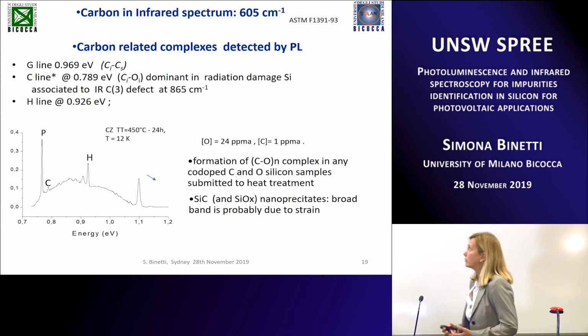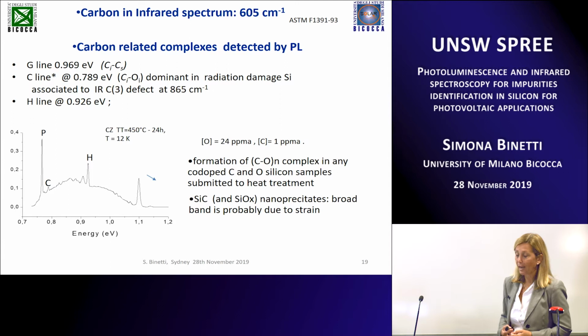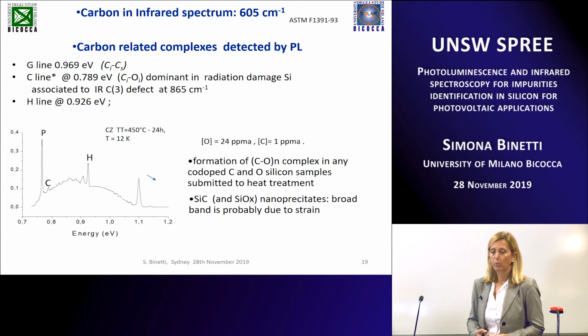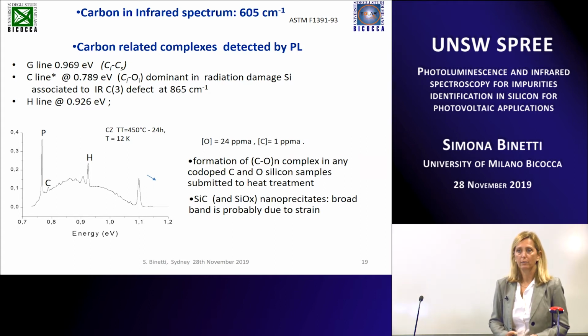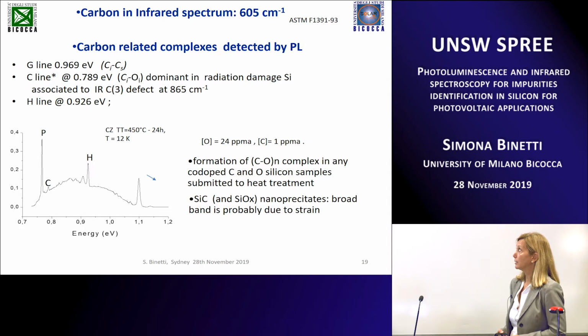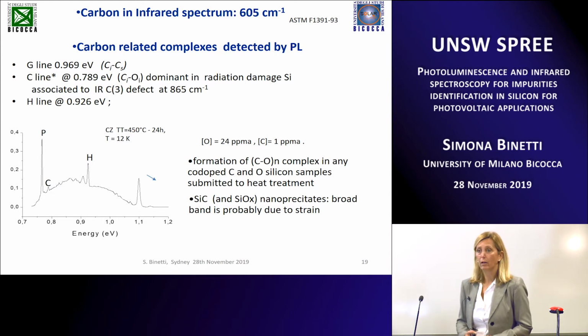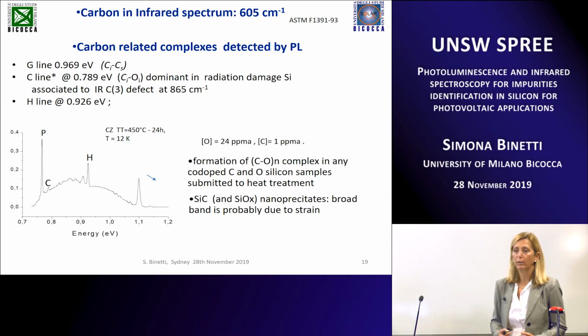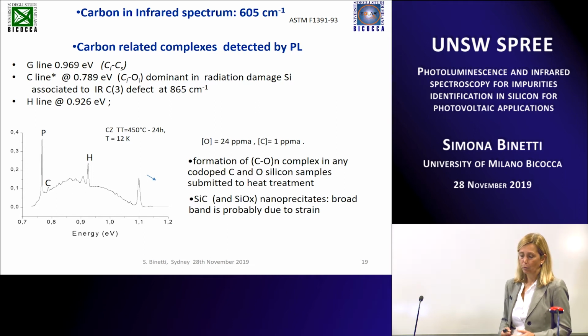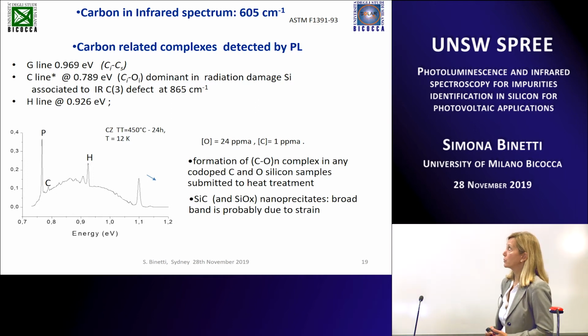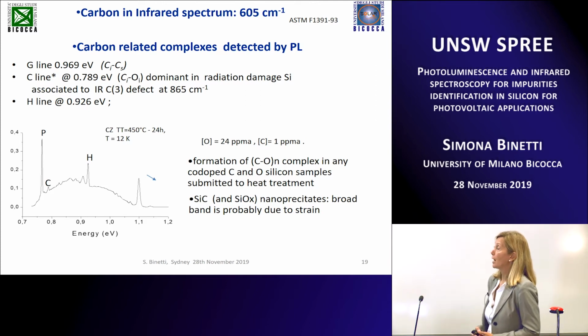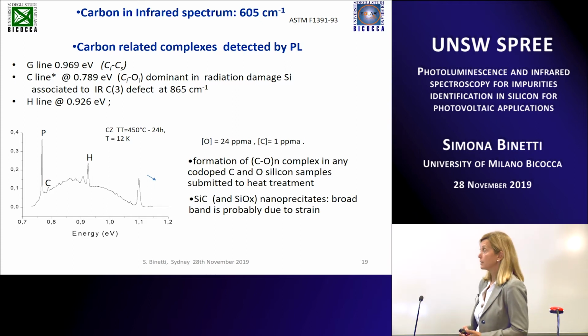Then let's move to the most common, the most famous light impurities, oxygen and carbon. Carbon, it's very well known, can be detected by infrared spectroscopy just by checking the band at 605 centimeters minus 1. It's a standard routine measurement, even if you have to put some attention, because there is an overlapping with the two-phonon bands of silicon. But probably you don't know that carbon can be detected also by photoluminescence.